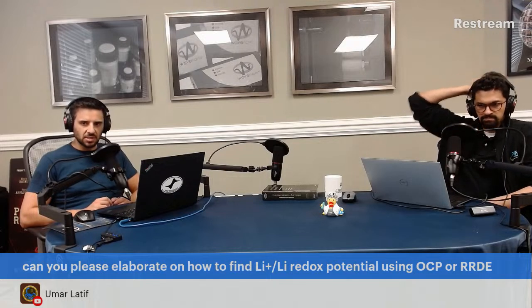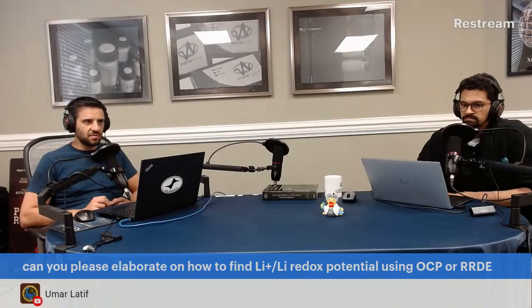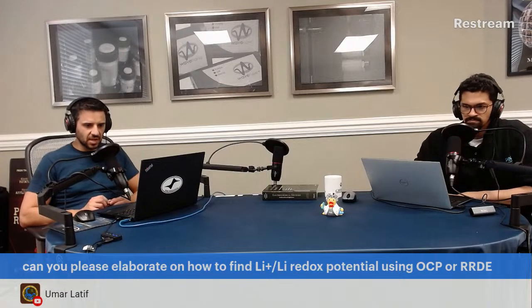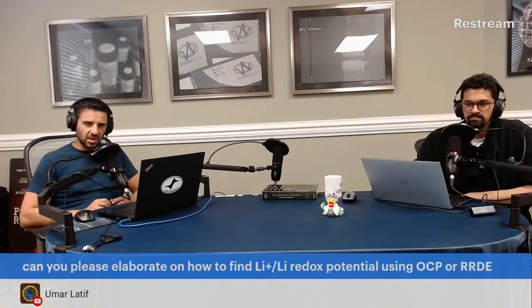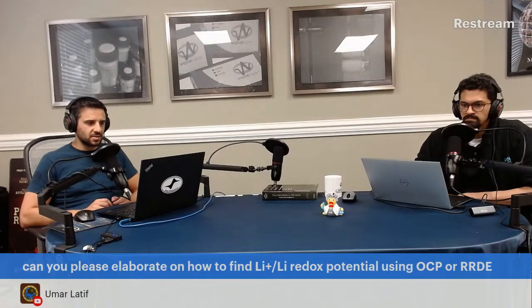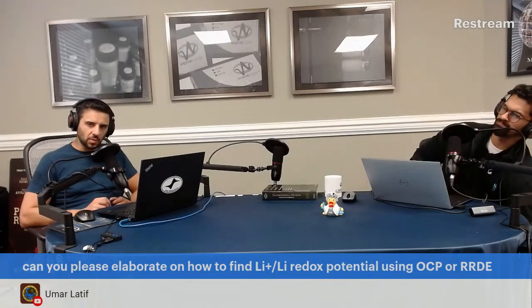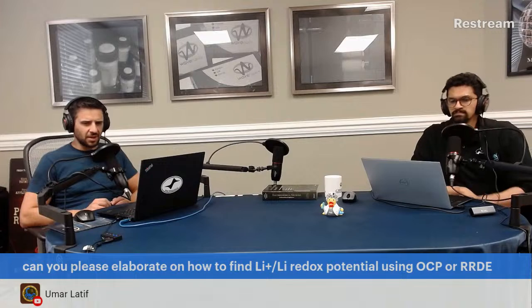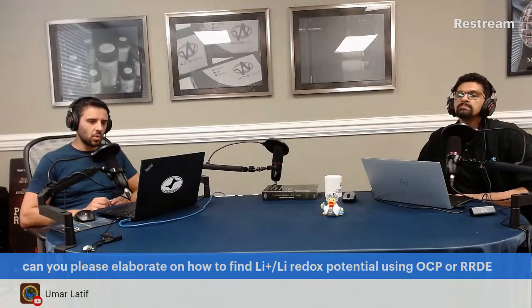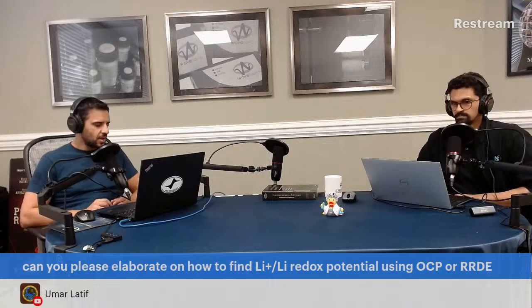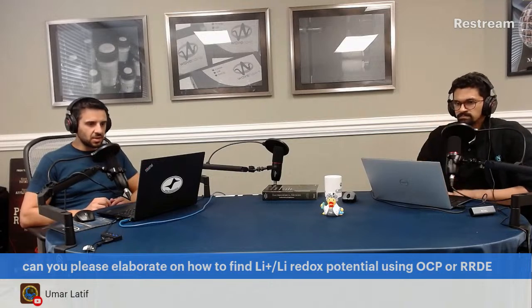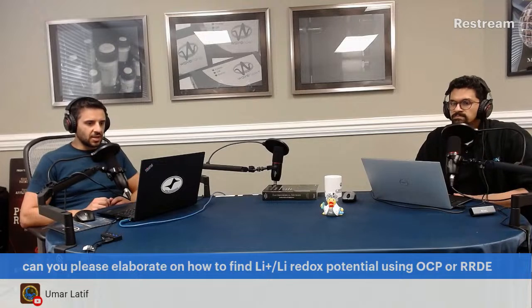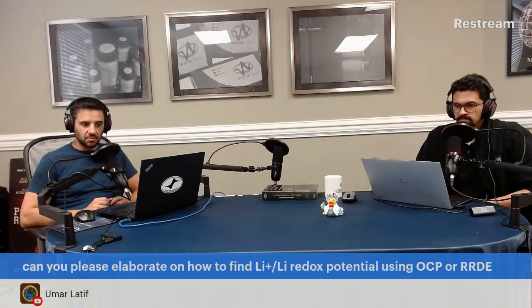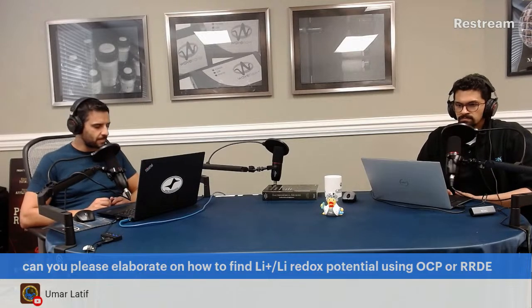A lot of times you'll scan no more than 2 to 4 or 5 times at most, because usually the first scan involves things like the SEI formation. So your first CV will be different than the subsequent ones. You'll usually have a big reductive peak that corresponds with the SEI formation. It won't appear in the next CVs. And then you have peaks, and those are the peaks of the process under study, right? That's how you can find the redox, and roughly what potential or voltage its process of interest is occurring at when you're using the material.